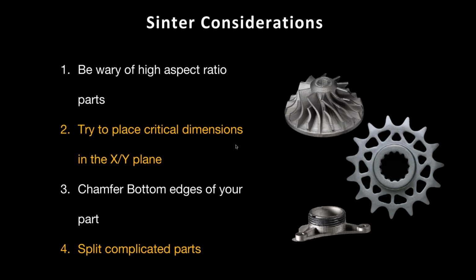Again, put the critical dimensions in the XY plane. Chamfering the bottom edges of your part may also help it shrink more uniformly, and you won't get any dimensional distortion. Also, sometimes it's helpful to split complicated parts. Splitting these parts may help it fit into the sinter furnace, or it could help in your sintering. So again, if you have that high aspect ratio part and you just have a top-heavy part, instead of trying to add more support material or a cantilever, you can always split it up and then bolt it together later.